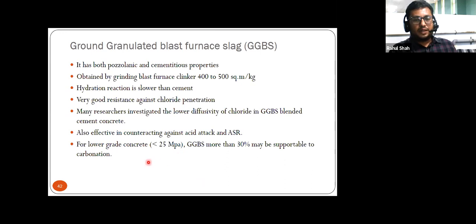So one thing is very evident: for lower grade concrete, when we are using grade 25 or let us say 20, right? When we use GGBFS at more than 30 percent replacement, it may be susceptible to carbonation. So when there are chances of carbonation and your strength is lesser, it is not advisable to use this slag, right? This is the most important thing that we should take away. For lower grade concrete, GGBFS more than 30% is not at all recommended, considering the durability aspect, although it may increase the strength.